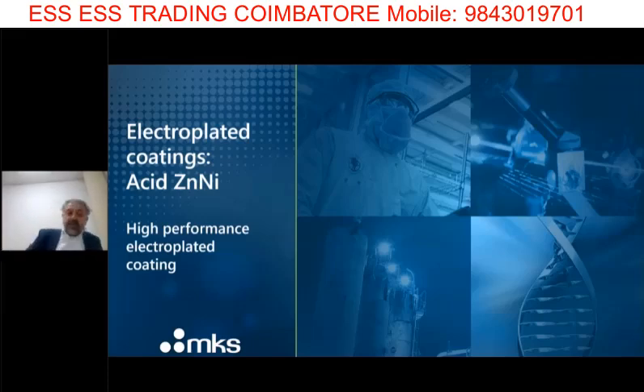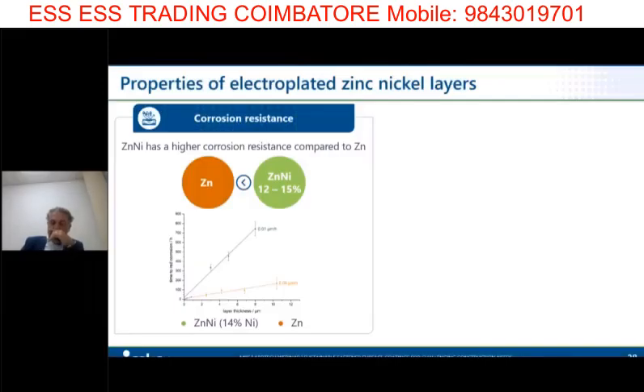In this case, it's helpful to introduce the Acid Zinc Nickel, and I will briefly show you the main difference between zinc and zinc nickel, starting from the corrosion resistance. Zinc nickel has a much higher corrosion resistance compared with the zinc. To give you some numbers, you can see this simple chart, where on the X axis you have the microns of zinc or zinc nickel.